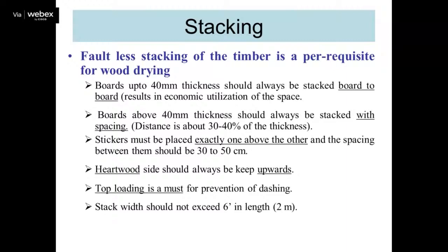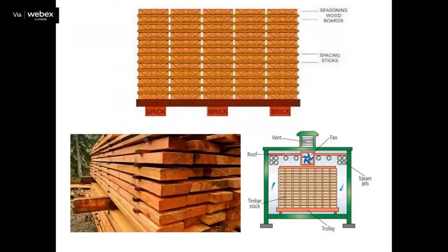The stack width should not exceed 6 feet or 2 meters. These are some stacking pictures that we can see here, where all the stickers are placed in a uniform way, and the planks are stacked properly, one above the other. Therefore, the distribution of the weight is proper, any deformation which arises in one plank can be minimized by the weight of the adjacent planks above it, and the air circulation also is proper.